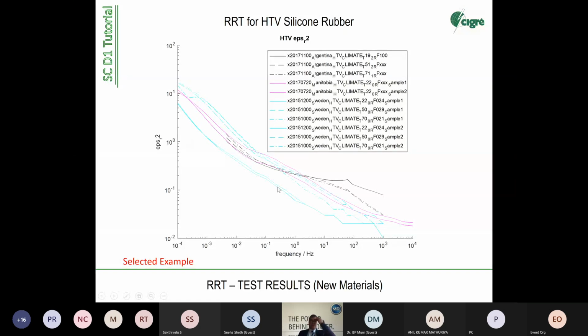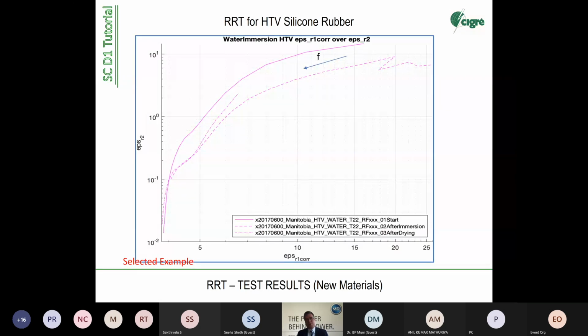And for example, this material we have also immersed in water. And now we come closer to the semicircles. Yeah? So this is Maxwell-Wagner, what's going on here. What we see is the left half of the semicircle. So because on the other hand, it would go down again. Yeah? So maybe here's the top or the top point of the circle, and it will increase and decrease in this direction again. So this is a cutout of the Maxwell-Wagner circle, which is perfectly given here.